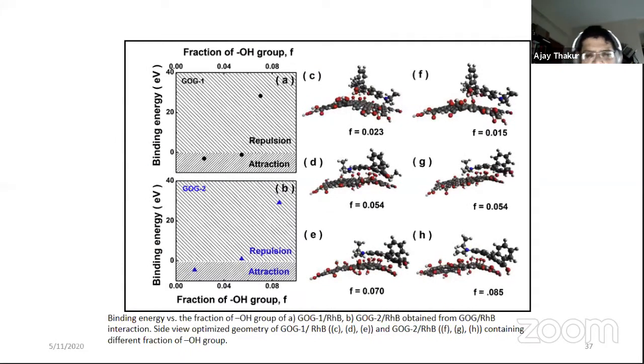And here in this figure, the take home message is, as a function of fraction of OH group, the attractive nature of the dye with the graphene oxide goes into a repulsive interaction. And therefore, a typical graphene oxide layer does not adsorb a specific dye in lieu of other.